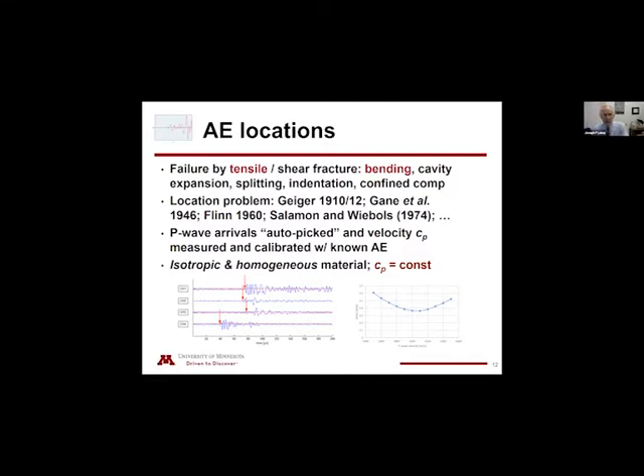The location problem, as I said, has been well studied. For us, the problem is not that difficult in the sense that our material is more or less homogeneous. For the most part, we work with rock that's fairly isotropic. So the location problem is not difficult. Because of the amount of data that can be generated, picking the first arrival is usually done through some algorithm. For example, I'm showing an acoustic event that is a signal recorded on 4 channels.